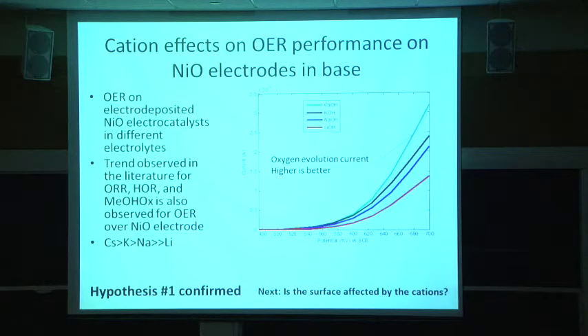Okay, so if we ran the experiment. Here we're looking at steady state currents. This is a little bit different than a cyclic voltammogram. Here we set a potential, measure the steady state current, increase the potential, measure the steady state current, and we do that to get rid of all the capacitive charging and all of the charging associated with oxidizing the surface. So these are actually all oxygen evolution currents.